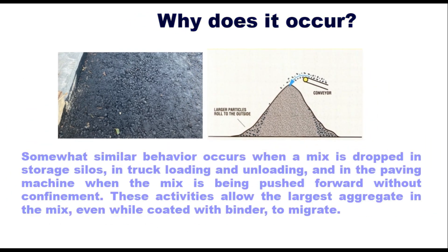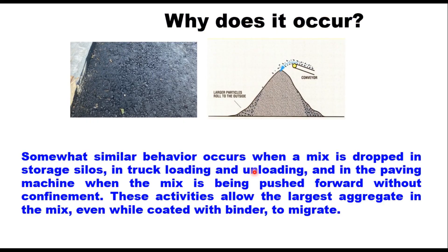Somewhat similar behavior occurs when a mix is dropped in the storage silos, in truck loading and unloading, and in the paving machine when the mix is being pushed forward without confinement. These activities allow the largest aggregate in the mix, even while coated with binder, to migrate, and that causes the segregation of the mix.